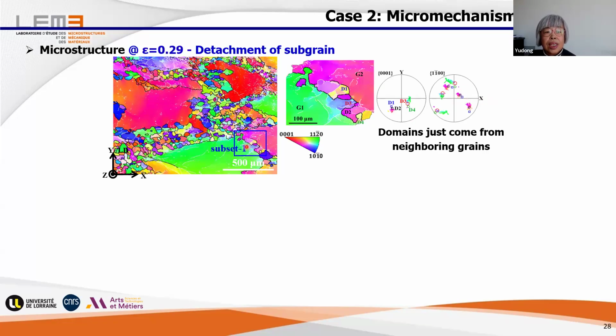For example, here we have only one layer of fine grains. And we have two matrix grains, G1 and G2, and we have small domains, D1, D2, D3, D4. You see, but maybe not very clear here. And then we just simply plot the pole figure of these two parts with the G1 and G2 grains inside. And you will see D1 and D2 orientation is very close to the purple grain, and D3 and D4 is very close to the orientation of G1.